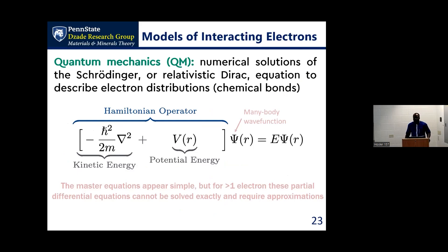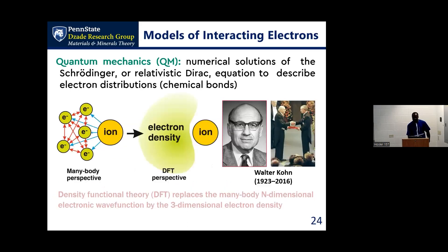That means we have to go to a different type of model — not just molecular mechanics — and that is when quantum mechanics comes in. The key thing is we want to solve a particular Hamiltonian, which we call the Schrödinger equation. That is the master equation. If we could fully solve it, life would be easy for us — but technically it is only for a one-electron system; even the highest supercomputers would take forever. So approximations are needed. The breakthrough happened around 1964 when Walter Kohn, a physicist who won a Nobel Prize in chemistry, developed what we call Density Functional Theory (DFT). Instead of looking at electrons as a many-body problem, he treated all the electrons as an electron density interacting with the ions. That problem quickly changed the whole dynamics of materials design. Now we can use electron density to produce all the universal properties of the material instead of solving the individual many-body problem. That became a revolution and has been the main backbone to most of our material system designs to this day.